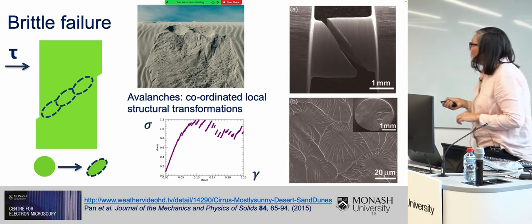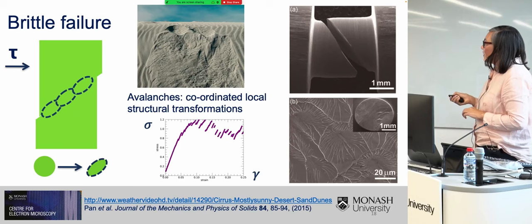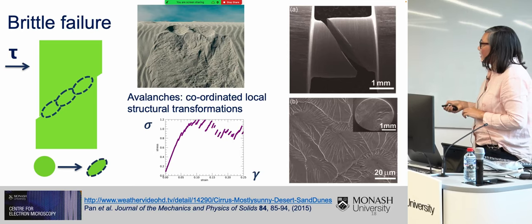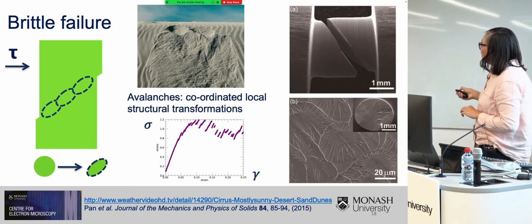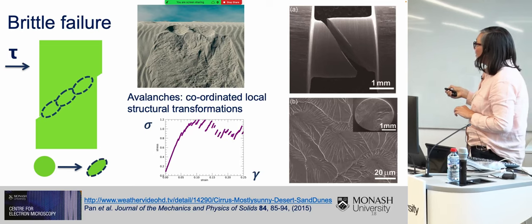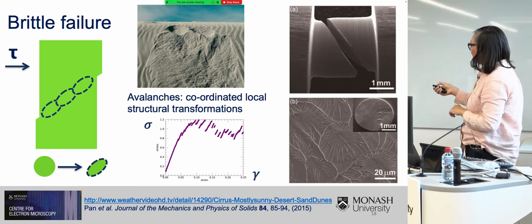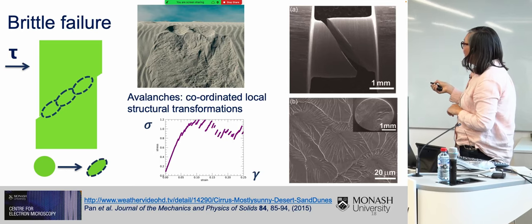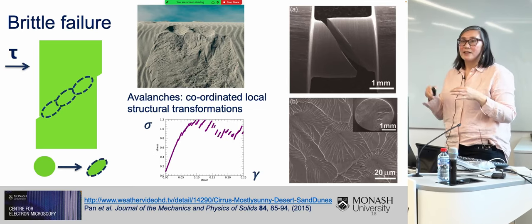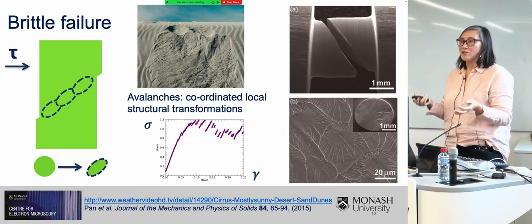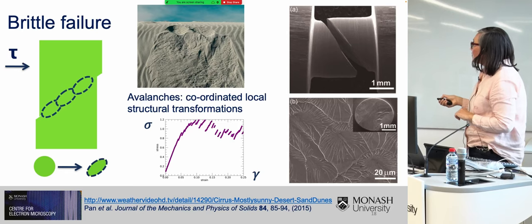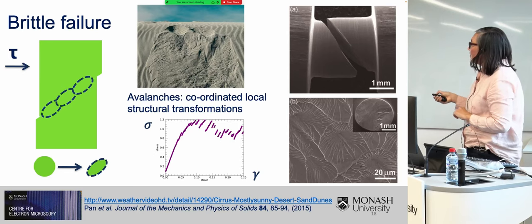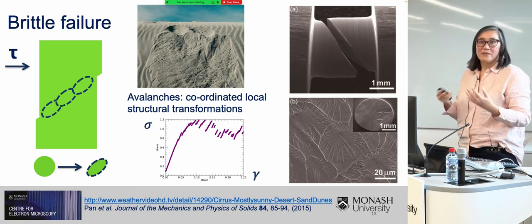But as I said, glasses often suffer from catastrophic brittle failure. And this is where you have some kind of structural transformation in a coordinated fashion in a single plane. And so over here you can see this is what's happened to this metallic glass. It's been pulled apart and it's failed in a single plane. And this is actually quite related to the kinds of avalanches that you get in granular materials. So if, for example, you compare this scar in a sand dune to the fracture surface of this metallic glass, then you can actually see similar patterns.